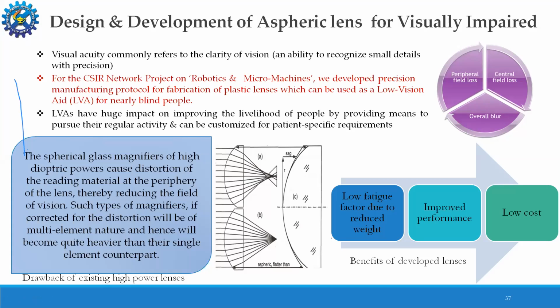So we have developed a precision manufacturing protocol for the fabrication of plastic lenses, which can be used as a low vision aid for the nearly blind person. The drawback with the existing system was that they use a spherical glass magnifier of very high diopter. They cause distortion at the periphery, which reduces the field of vision. If such magnifiers were corrected for distortion, they would become multi-element in nature, and since they were made of glass and spherical, the entire system becomes quite heavy and cannot be worn for a longer time. So what we did is that